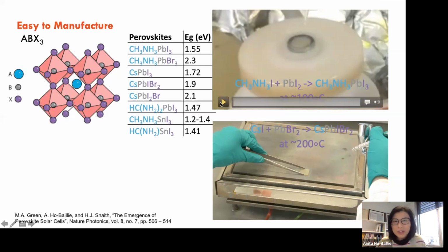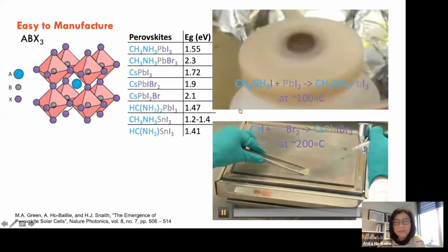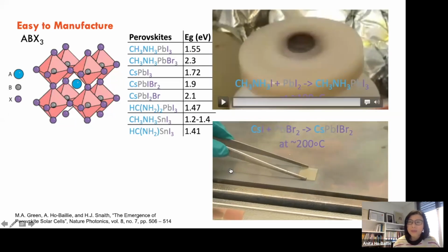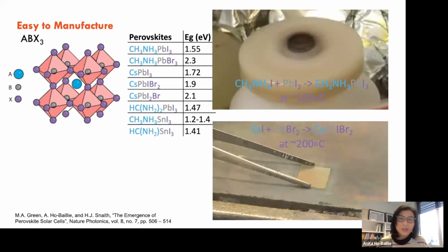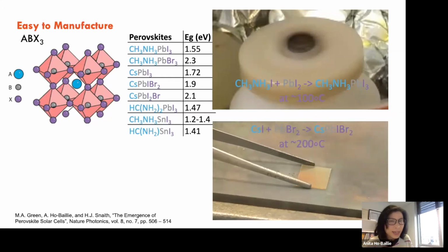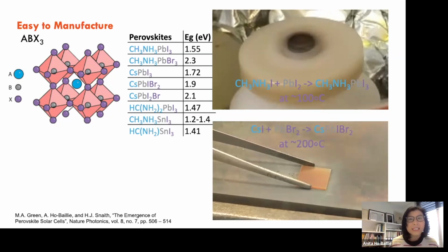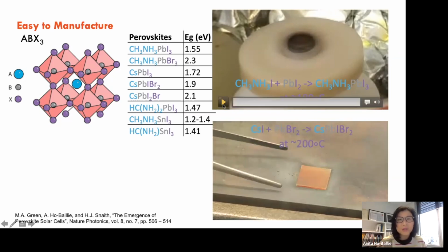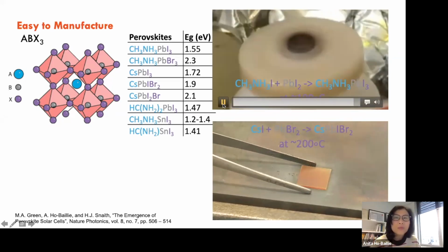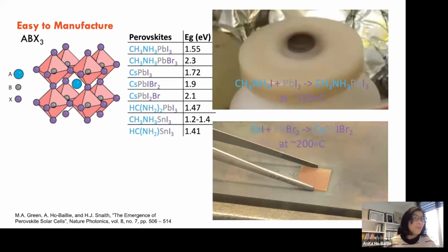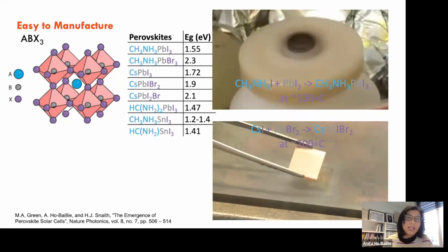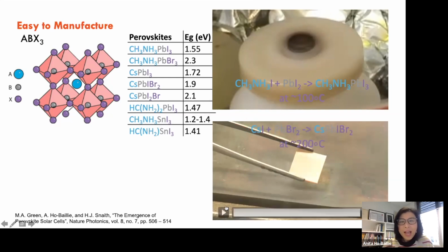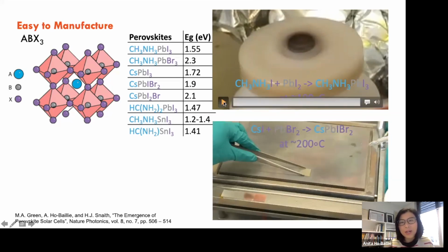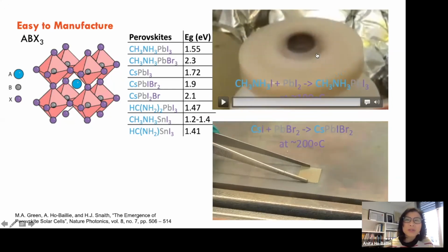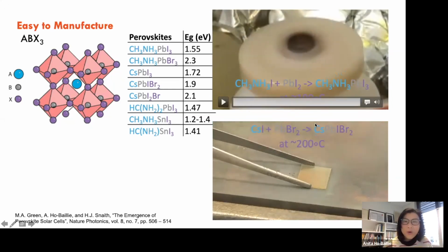It's very flexible in terms of the way we make them. If you remember, I showed how to make the silicon cell, and you have to basically purify it from sand or quartzite. Whereas with this one, we can make it by dissolving the precursors into solution solvent form, and we can deposit it onto a substrate that holds the solar cell, because it's so thin and needs something to sit on. You can do it by spin coating, meaning you can spin the material across the substrate to spread it, or you can even spray it.